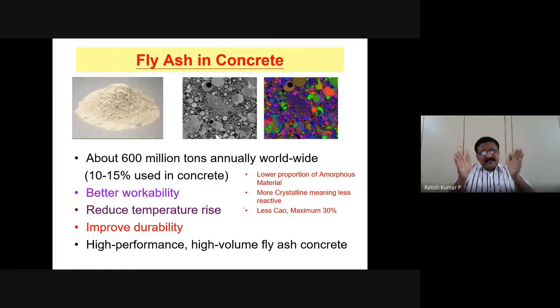Obviously, when the acidity increases, the alkaline passive layer on the steel is going to get broken. It becomes active for corrosion. So that's one point. Of course, there are very good advantages of fly ash, and there is also an abundant amount of fly ash available as compared to the slag I'm talking about, not as compared to limestone.